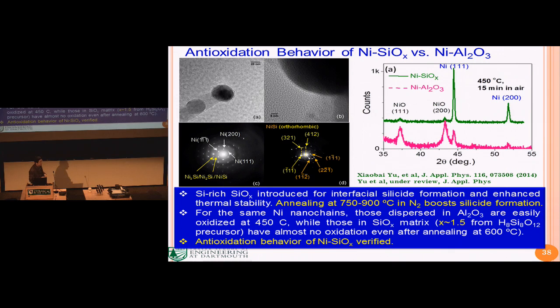I happen to have some experience with silicides from when I was a master's student. Silicides are conductive, highly stable, and they're being used in practically every chip in our computers. Turns out that material is also equally suitable for increasing the thermal stability of nanoparticles. So we introduced a silicon-rich matrix. Silicon usually forms silicon dioxide, but we introduce a matrix that contains x equal to 1.5. That means the matrix is silicon-rich.